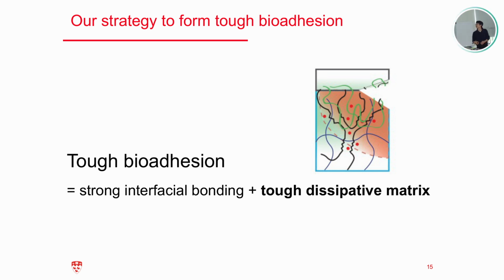In terms of the gamma 0, the intrinsic bonding, we can already make it the highest we can get, and the tissue doesn't contribute a lot. And the last one, the adhesive matrix, has no physical limitation, and therefore we can focus on that to achieve a tough bioadhesion. So our recipe to achieve tough bioadhesion essentially is to focus on the third term. We need to use a very tough and dissipative matrix in pair with a very strong interfacial bonding, and we can get a tough adhesion.